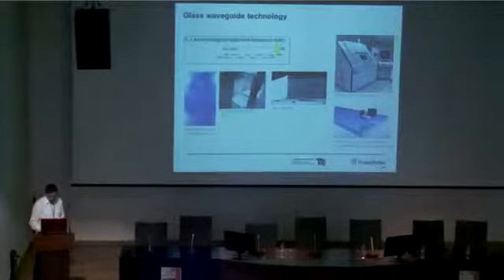So we don't need any post-polishing processes. We can decide how we want to cut it. If we have a panel, we can cut it to smaller pieces, or just cut the border around, so that we really have an interface to such a panel. We can also cut wafers to smaller pieces, for instance, for PCB embedding tests. And it's similar with the wafer size process. There we use spin coating and mask aligner, and the diffusion process is the same, and then we cut it. And for instance, for the Foxtrot project, we cut glass slides 20 by 90 millimeters,